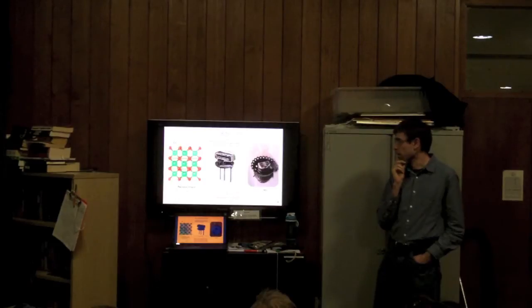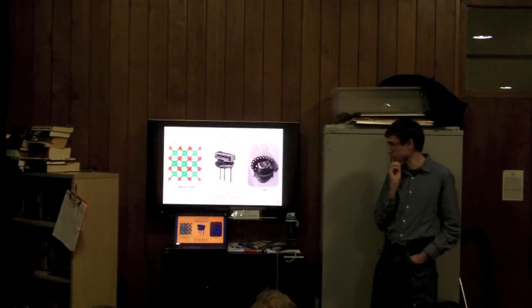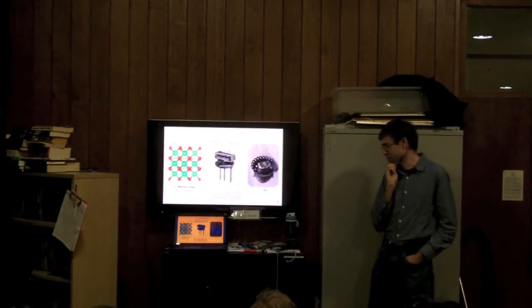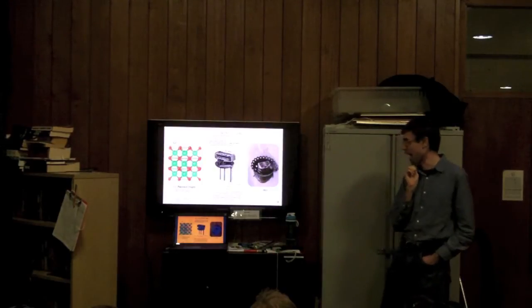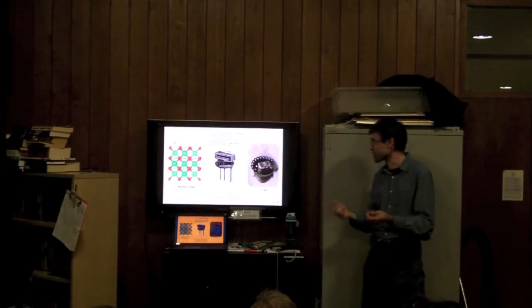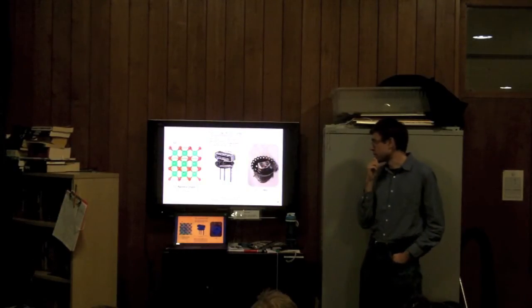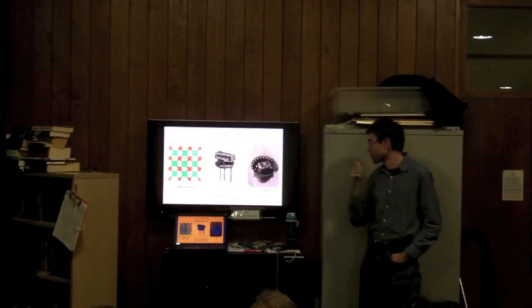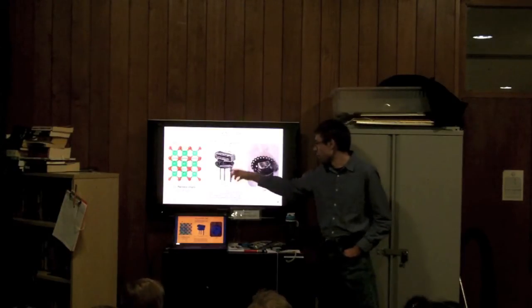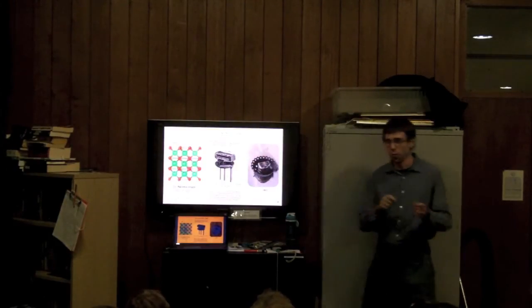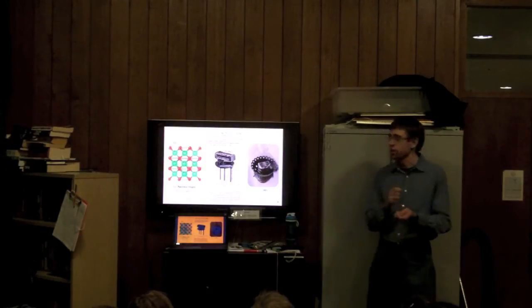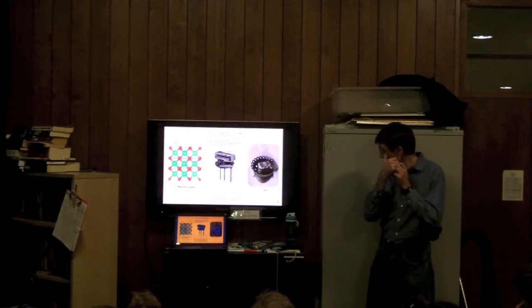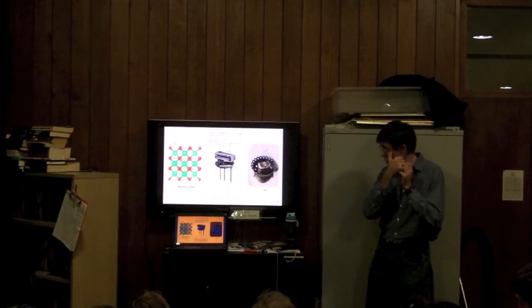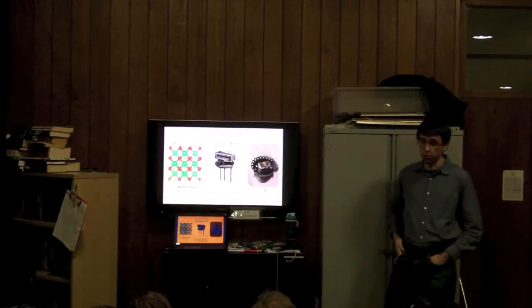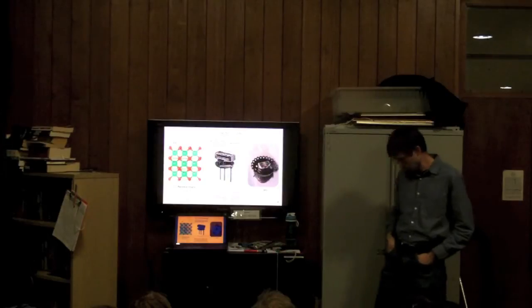A bit later on, Walter Nernst, a pretty famous chemist, came up with this awesomely named thing called the Nernst glower, which is literally just a bit of ceramic. It's a zirconium yttrium oxide. And again, he didn't really know what to do with it, but he stuck it in this Nernst lamp. You heat it up to about 500 Celsius, you apply a current to it, and it produces this lovely orange glow. And for a long time, up until about the 1920s, these were considered to be direct competitors with the light bulbs that were being produced in America at the time.